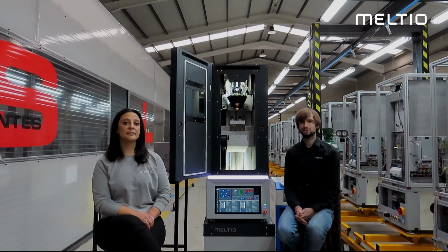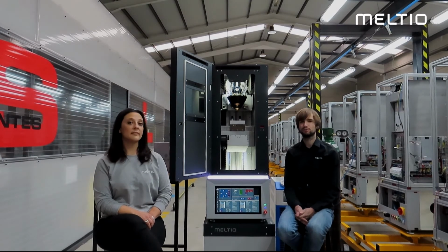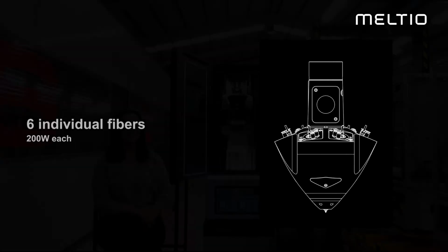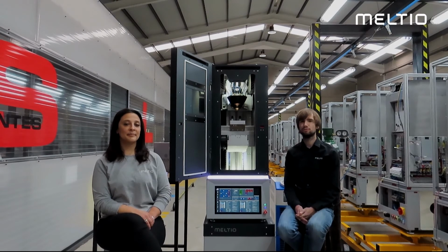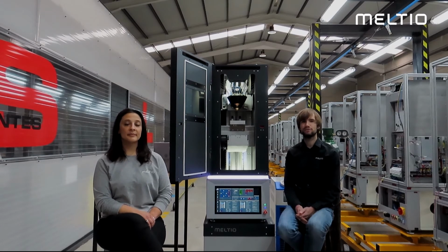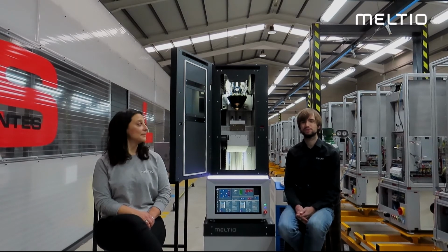We achieve this very low cost of the laser by using an unconventional approach, because we don't use a single high-power laser source. We split the output across multiple lasers that are fiber-coupled into the deposition head at 200 watts each. The output is then combined at the focal spot to deliver 1.2 kilowatts. Using this method of beam combination allows us to use direct diode lasers that would normally have to be combined as pump sources in a very complex high-power laser assembly. And using them directly allows us to drive down the system cost and increase the system lifetime, because we distribute the optical energy across multiple systems, and the energy densities throughout the system are much lower. Before we go into more detail, Amanda will give an overview of the machine specifications.